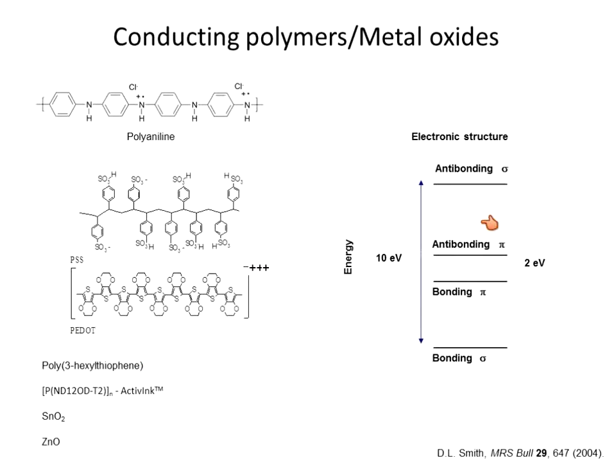And if you see to the right, we see the electronic structure of these polymers. Basically, they are conjugated, which means that they have a lot of double bonds, as you can see here. The important part of this electronic structure, which gives it all of its electronic properties, comes from the bonding, anti-bonding pi-pi star overlap. That's the important part of the electronic spectrum. The in-plane bonds, the sigma and the sigma star, are so high or so low in energy that they do not contribute.